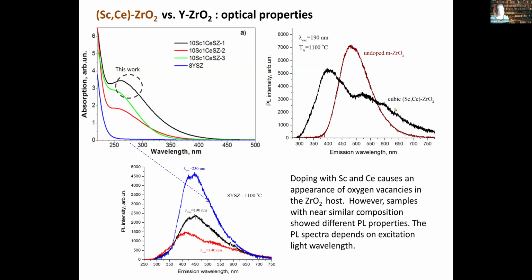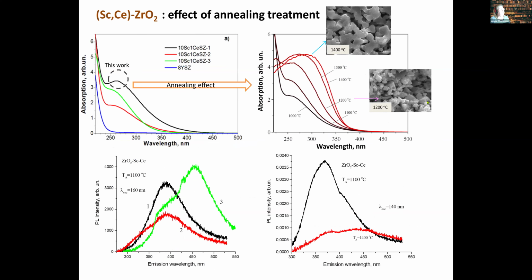But when we started to look at what happened with optical properties in terms of their light emission, we discovered that they have completely different luminescence. We cannot simply group yttrium doped materials with undoped materials and with scandium and cerium doped ones. So all the different dopants produce different defects. And for us, it was also important whether we can control them.